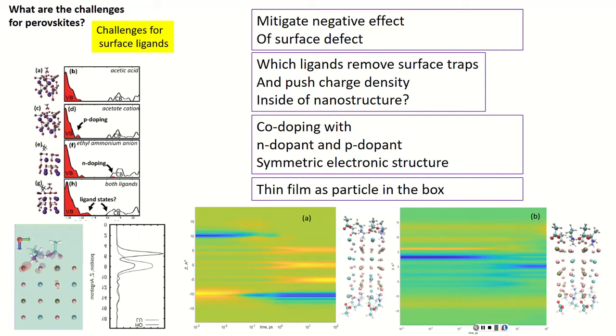There is a question to which literature doesn't give an answer. The perovskite lattice can be considered as sub-layers rich in cesium, this cyan, balanced with bromine, and then lead, which is kind of goldish, with bromine. So cyan or lead, cyan or lead. On which surface can one adsorb the same ligands on both surfaces, but which one is more preferential to have a better light emitter? And in order to address this question, Daniel did try to put the same distribution of ligands on either the cesium-rich surface or, well, we do not see it here, the lead-rich surface.